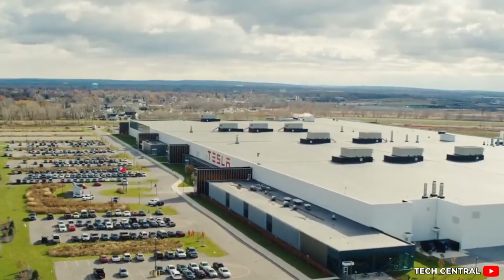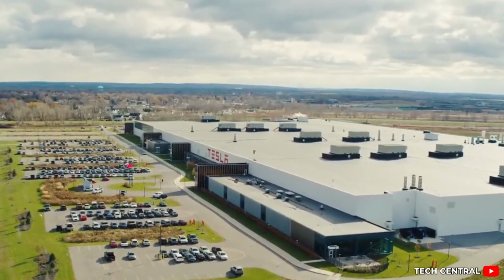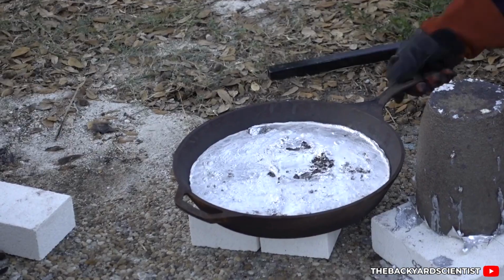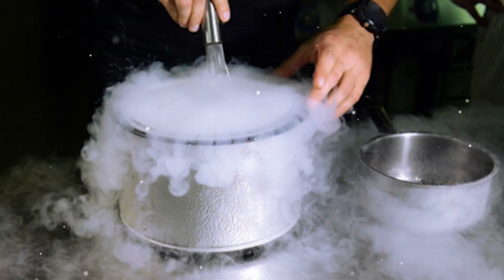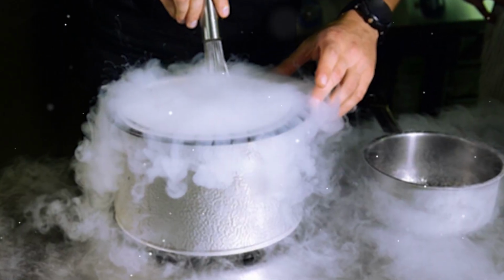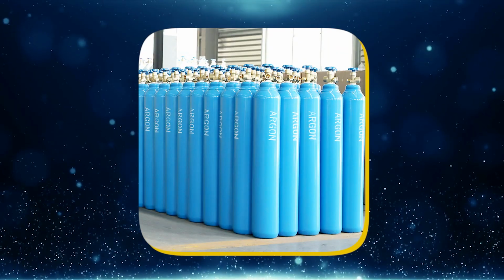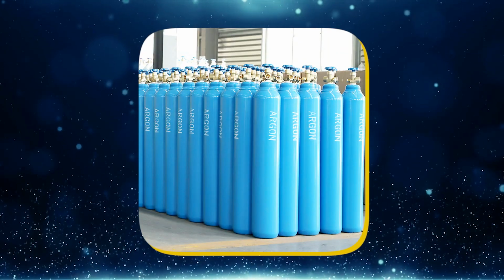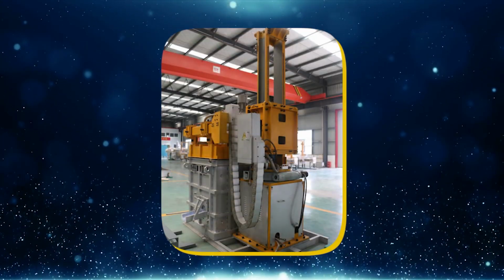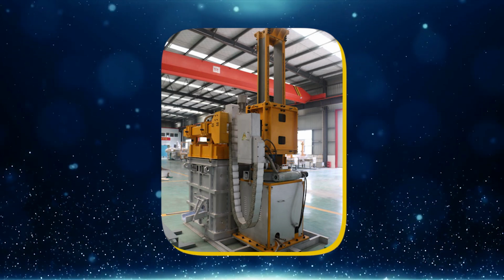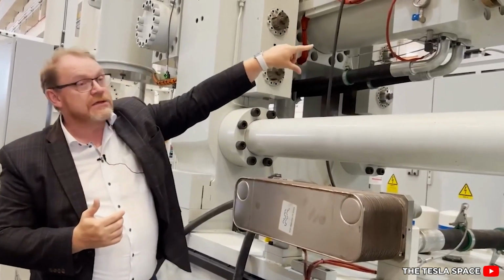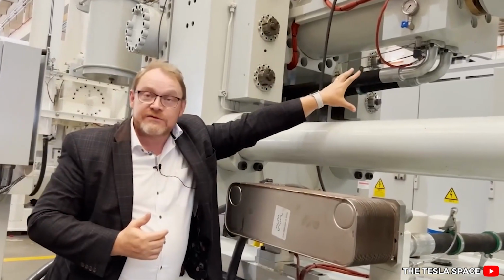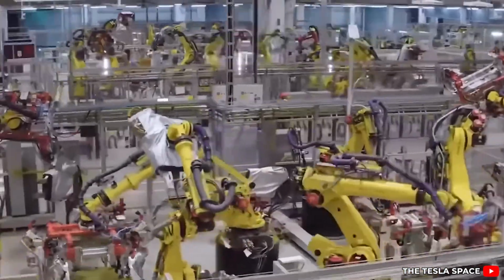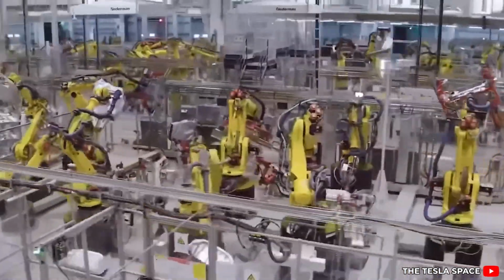Inside this holding furnace, Tesla fills the open space with nitrogen gas. Why? Because when molten aluminum meets oxygen, things get messy. Oxidation ruins purity. Nitrogen solves that by keeping the oxygen out and the heat in. And to go a step further, operators also pump in argon gas, run a rotary degasser, and pass the alloy through a silicon carbide filter. This final step pulls out any particles larger than 25 microns. Tiny, yes, but big enough to cause real trouble in a part that needs to be perfect.